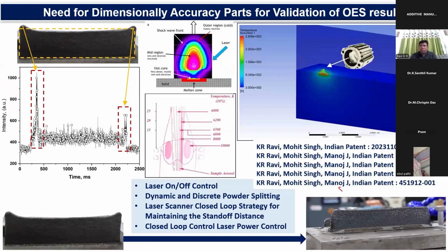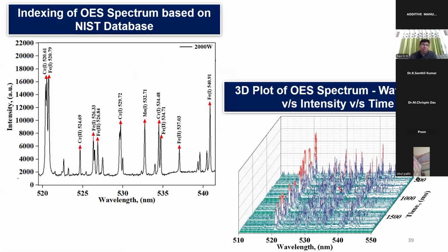So what do we measure actually? When we do the laser metal interaction, plasma is created above the top of the surface. This plasma we take to the detector, which measures the plasma plume intensity. The plasma plume intensity will look something like this. It will have a spectrum with different wavelengths. Each peak corresponds to a particular element. Again, these are arbitrary units.